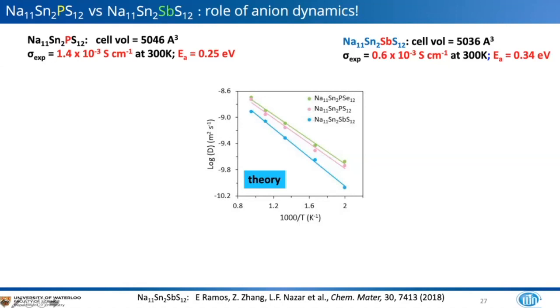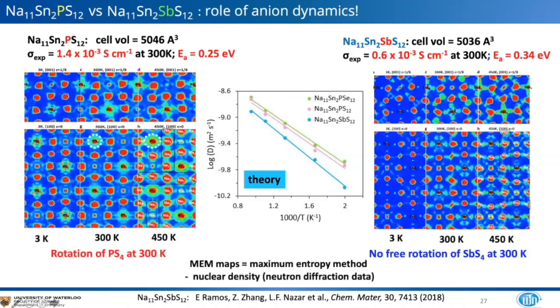And this is also borne out by our theoretical calculations, where you can see that either the sulfide or the selenide have a lower activation energy of about 0.25 compared to that of the antimony analog. And the reason for this is actually shown in these maps. So these are maps obtained from neutron diffraction data. This is derived from the maximum entropy method, often abbreviated as MEM. And so this is effectively a map of the nuclear density. It's obtained from extracting the structure factors from the neutron diffraction data itself. And so what you see here for the phosphorus analog is the nuclear density, for example, for the sulfur around the PS4 groups. So the red blobs here are the sodium ion density in the structure, and this green density at 300 K shows the rotational motion of the PS4 group about this phosphorus position.